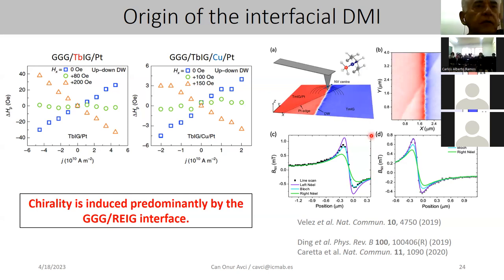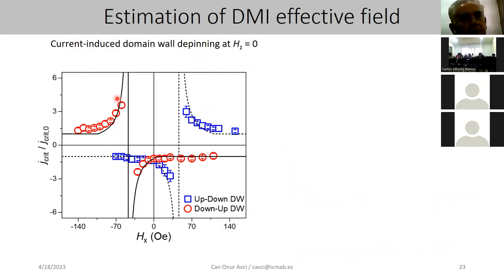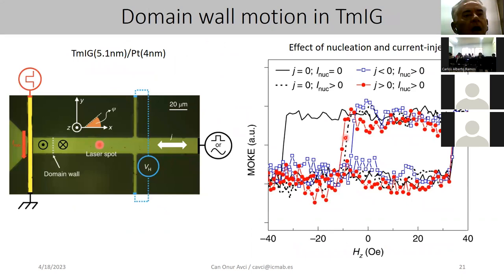This one. Yeah, that's right. Are these FMR measurements? These are not FMR measurements. These are the changes in the coercivity, so delta means the change in the coercivity as a function of current, in measurements that look like this. Delta is the difference between red and blue, for negative current and positive current. It changes to one side or the other side. It also increases linearly, which means that the domain wall responds to the current in a linear way, meaning that there's a certain torque.